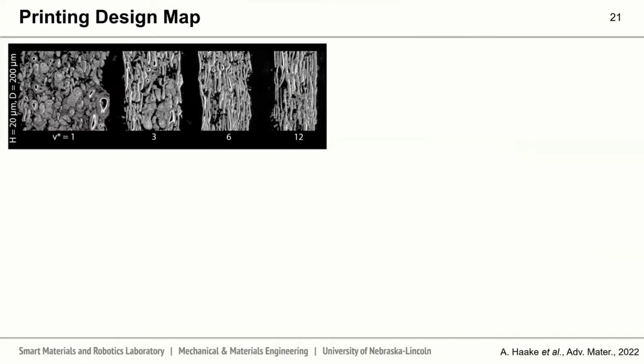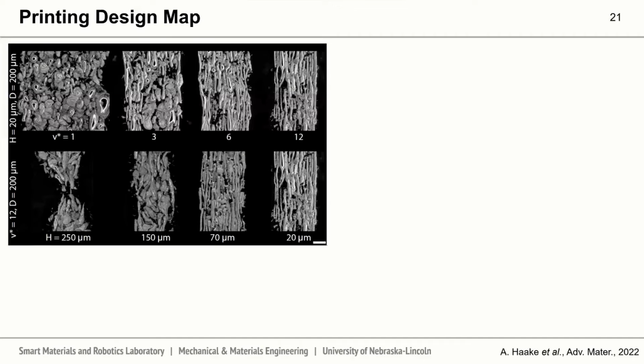From this, we observed a change in aspect ratio as V star, this normalized velocity, is increased from 1 to 12. We also saw an increase in aspect ratio as the height of the nozzle with respect to the print bed is decreased from 250 microns all the way to 20 microns.